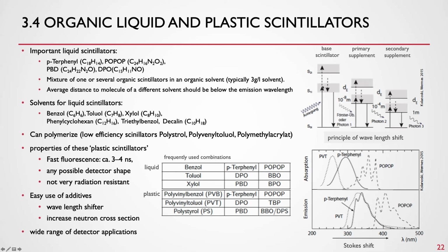Why is that so? We have a base scintillator that gets excited by the signal. Let's look at the absorption here for PBD. That's a mixture of PBD, p-terphenyl, and POPOP. Let's say we mix these three together. We have a very wide absorption profile over many wavelengths.